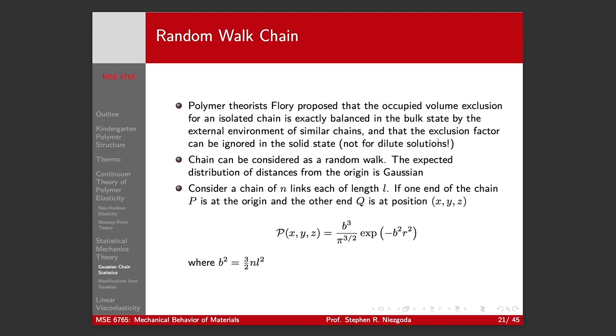Okay, so what does this mean? Basically, all he's saying is all the chains are seeing a very similar local neighborhood. So you can think about each chain independently rather than needing to consider all of the chains in the solid, right? And also that the external neighborhood doesn't affect things. Obviously, that's not going to be true for dilute solutions.